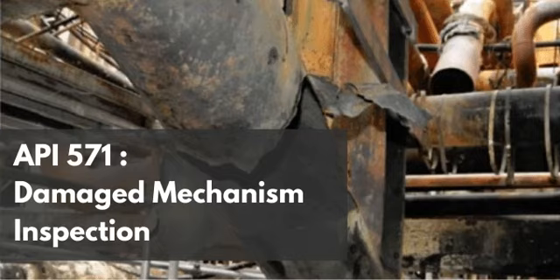And this doesn't just happen out of nowhere. You need a very specific triad to initiate this failure, right? Yeah, you need three things perfectly aligned. A susceptible material, a high tensile stress, whether that's applied or residual, and an aggressive chemical environment.